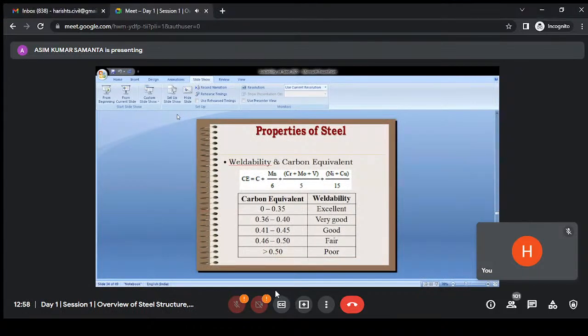Here is one point we have to take: if carbon equivalent is more than 0.50, then weldability is very poor. So in IS 2062, whatever the strength specified, if we go for steel with more than 350 yield strength level, its weldability will be poor. So in case, for certain advantage, you use 410 grade or 450 grade of steel, then we have to be concerned about the weldability. Welding should be automatic, like MIG, instead of manual welding like SMAW. So during fabrication, we have to take care of this issue. If we go for 410 steel with normal SMAW, that welding is likely to crack.